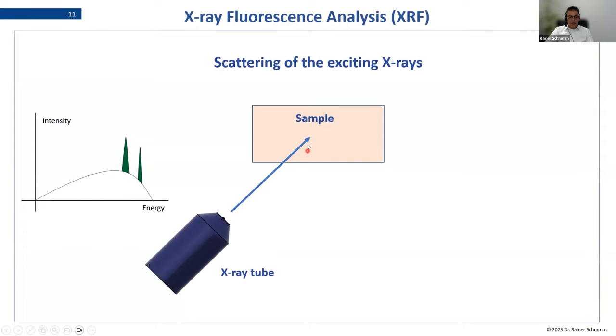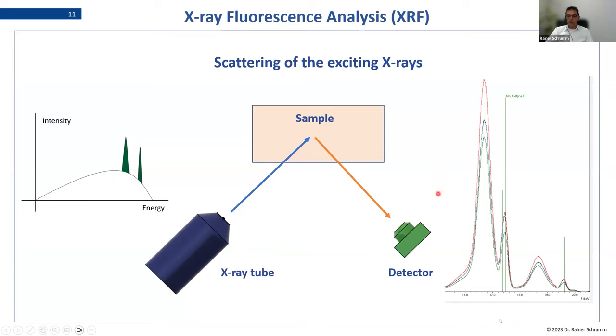And then this radiation is just scattered at the sample. So we are not talking here about fluorescence radiation. It is only the exciting radiation which is scattered at the sample, and there is a part which comes to the detector, and then the detector will register the intensities of this exciting radiation like this. So if this were a molybdenum tube, we will have our molybdenum characteristic lines, which are issued by the tube and scattered by the sample.